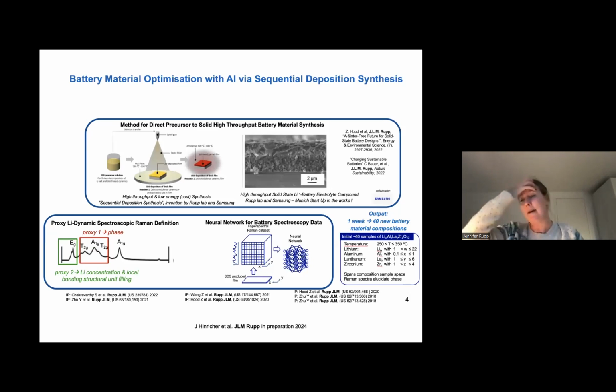So here's what we came up with. I just showed you before that we had this invention of the sequential deposition synthesis. And that's a great method because it directly allows you to go from a precursor into a solidified material that you see on the right, but you don't need any classic sintering. And what's beautiful is you don't create just loose powders where, again, whatever you measure has nothing to do with the material after integration in the battery. And I think that this is the way to go.